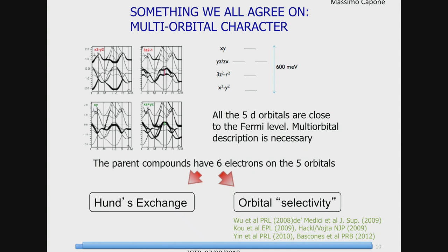We have that many bands cross the Fermi surface, and as a matter of fact, basically all the 5 d orbitals are needed for a reasonable description of the fermiology. This is because the crystal field splitting is small, and you end up with this very intriguing and complicated fermiology. We start from parent compounds, which happen to have 6 electrons in these d orbitals. So in principle, they might well have a Mott insulating ground state, even if they don't. And we have to understand why this doesn't happen. Of course, the simple answer is that the Hubbard U is small, but we'll see that the answer is actually a little more